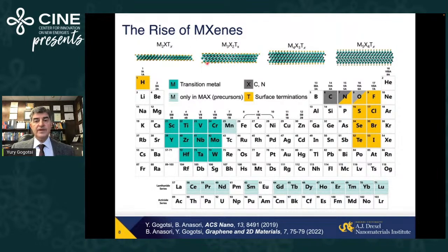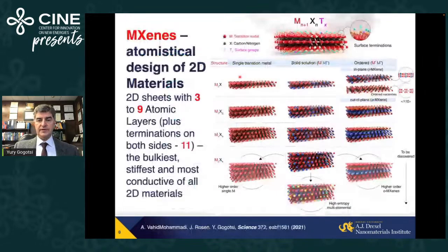But what is also important, if you have a transition metal, its surface will not stay pristine. Transition metals gladly share electrons with other elements, and oxygen, hydroxyl groups, amides, amines, and chalcogens and halogens can all be terminating the surface of MXene, forming something we mark as T. T stands for surface termination, X for carbon and nitrogen, M for an early transition metal. So it's MXenes, and the suffix 'ene' shows their two-dimensionality, like graphene, silicene, borophene, and other 2D materials.